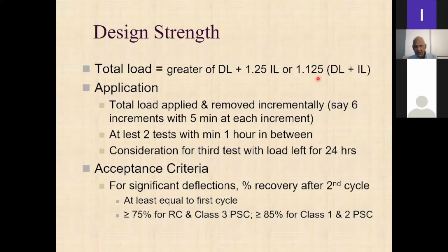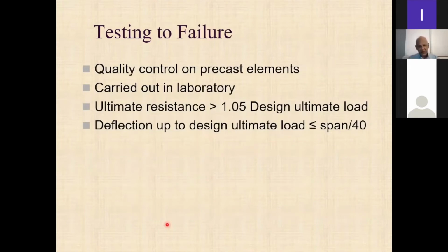So basically, if this is deflection and that is load, you load it and then you unload it and see whether it is basically in the elastic range. That is why the recovery has to be at least 75%. And the other approach, of course, is to test for failure, but this is typically done only for things like precast concrete elements.